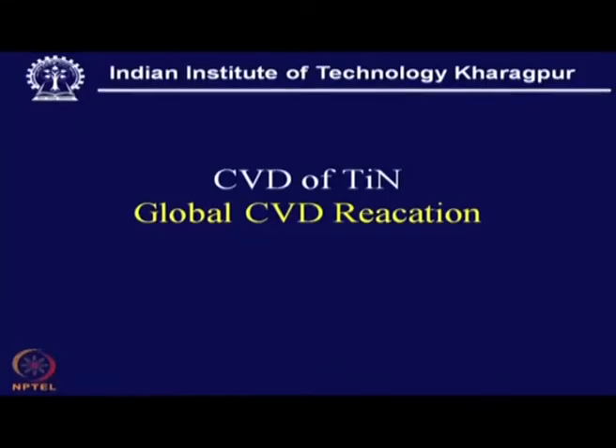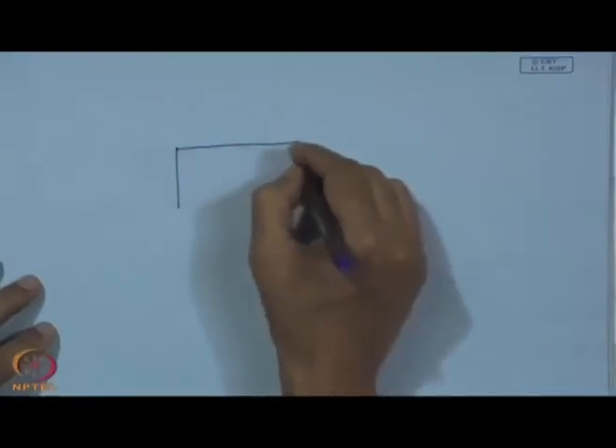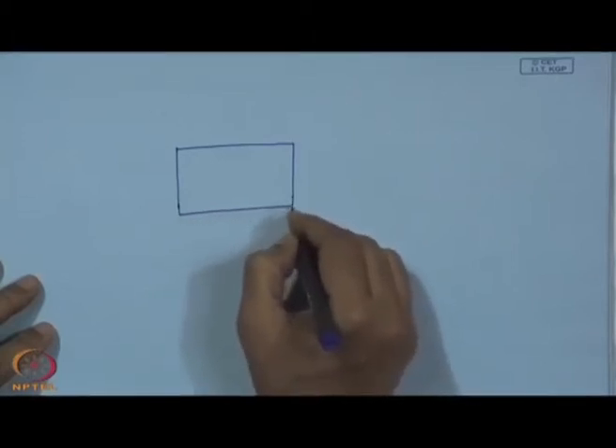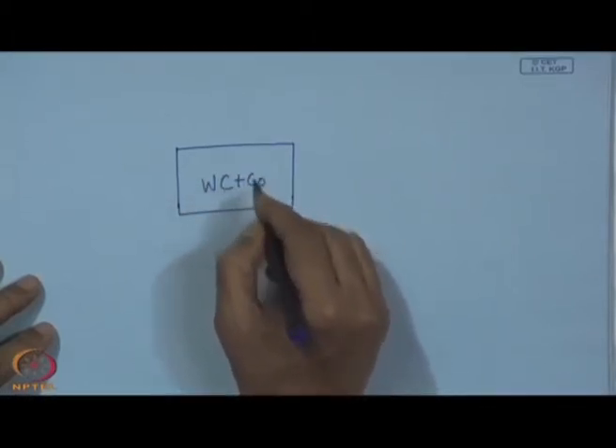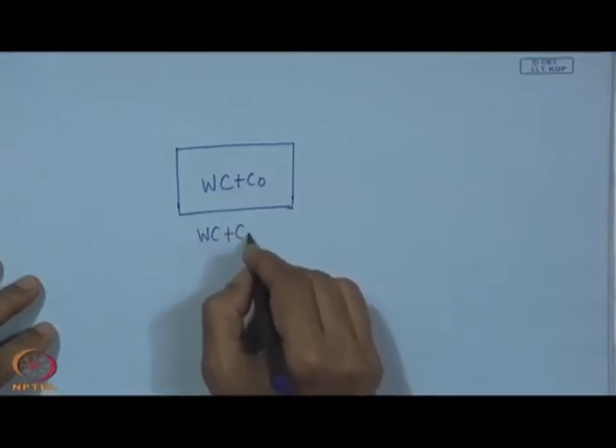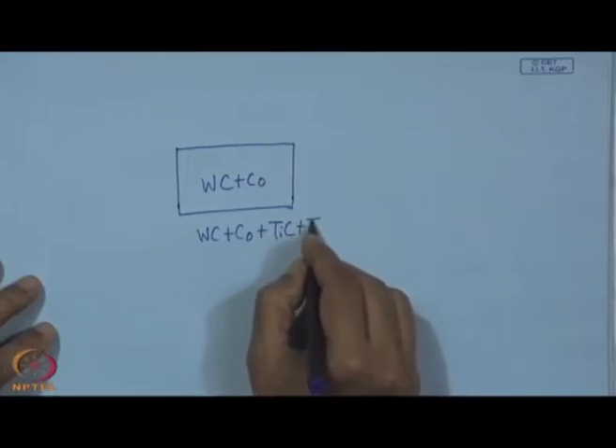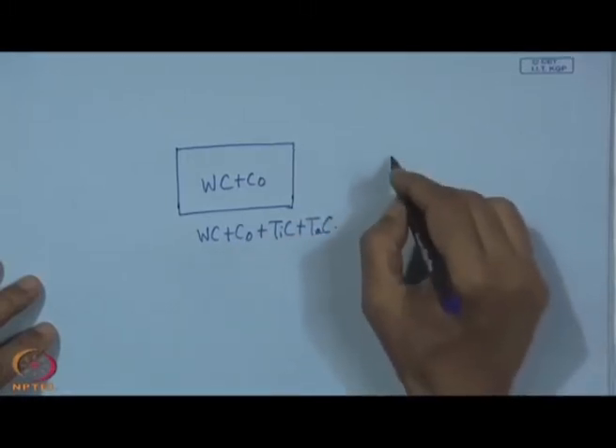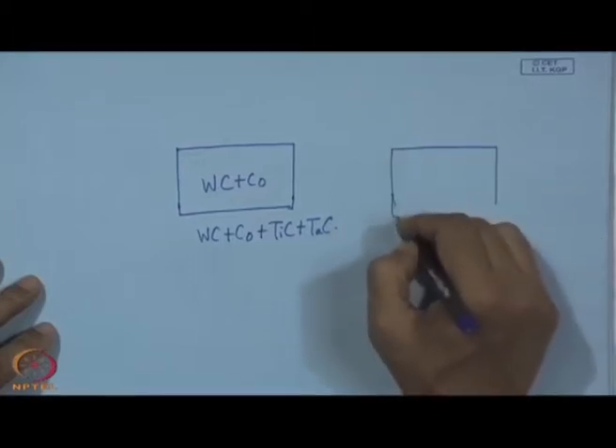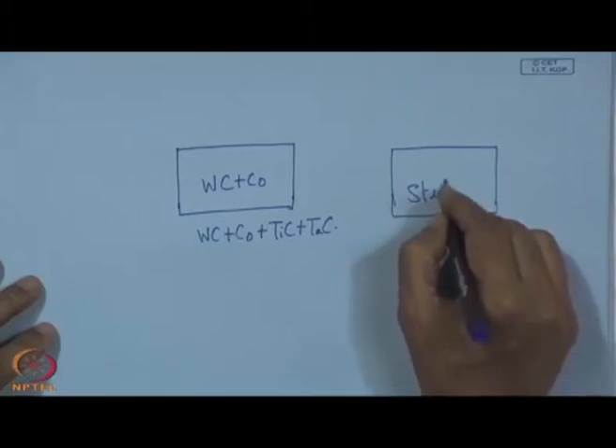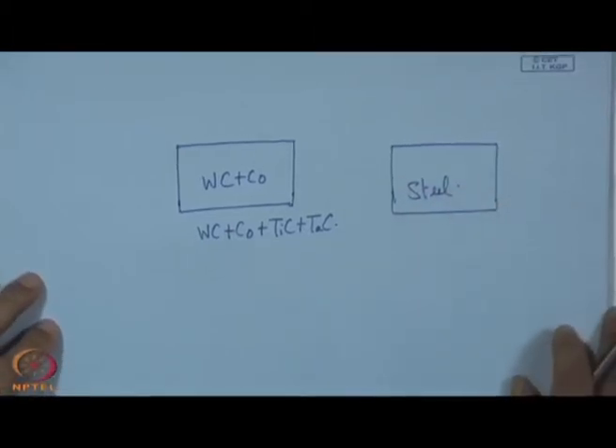Now, here comes the most important issue. We have such a block which is made of tungsten carbide and cobalt; it can also be tungsten carbide cobalt plus TiC plus TaC. These are routinely used. On the one side we have all sorts of steel families, which include HSS, high speed steel, die steel, tool steel, bearing steel, and these are alloyed steels consisting of molybdenum, cobalt and similar materials, chromium, vanadium, to enhance the bulk property.